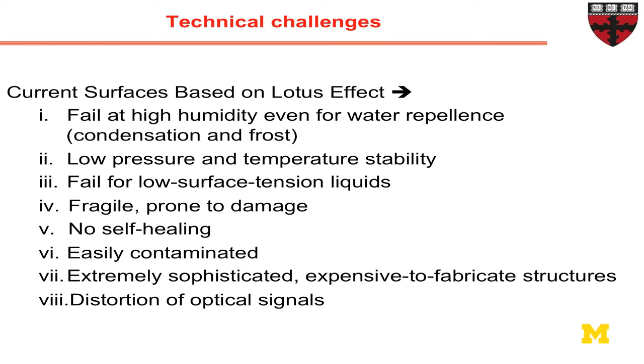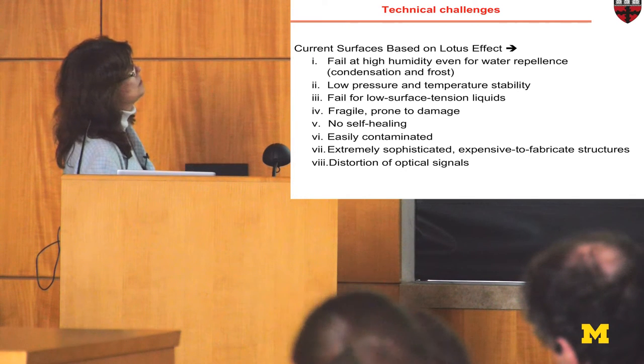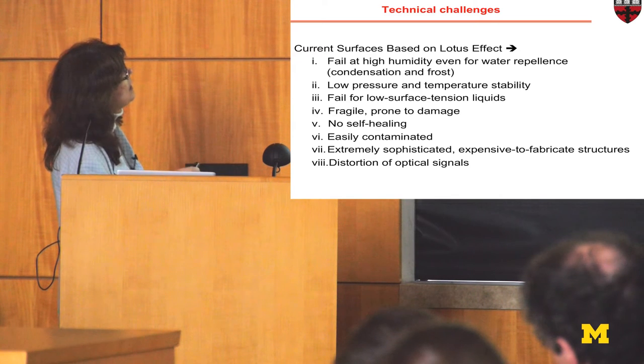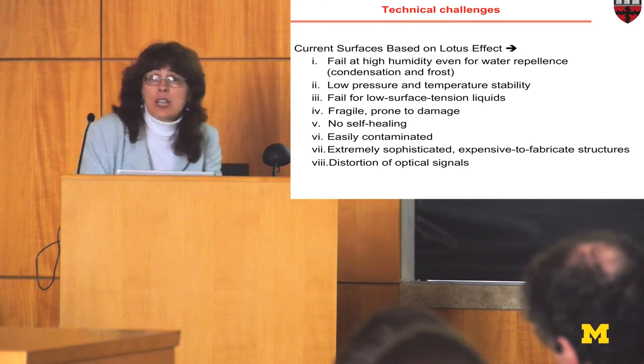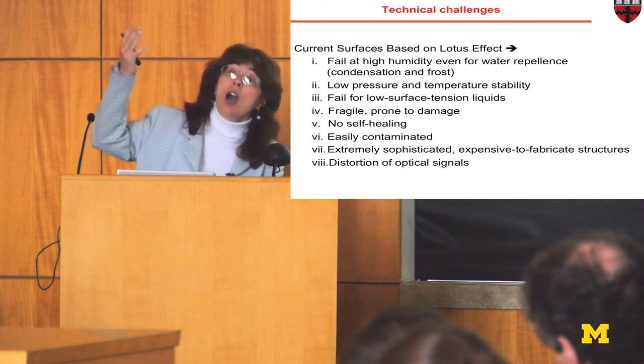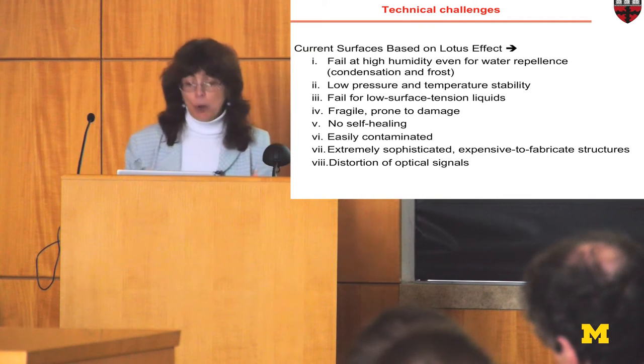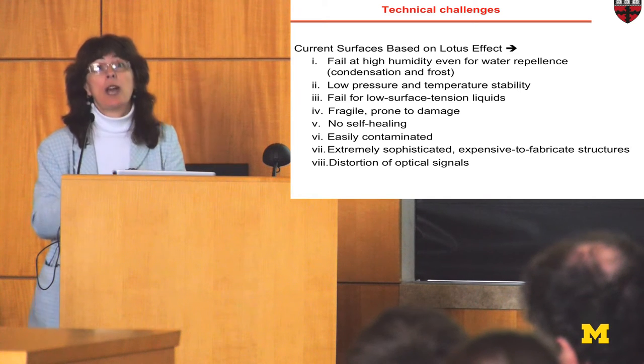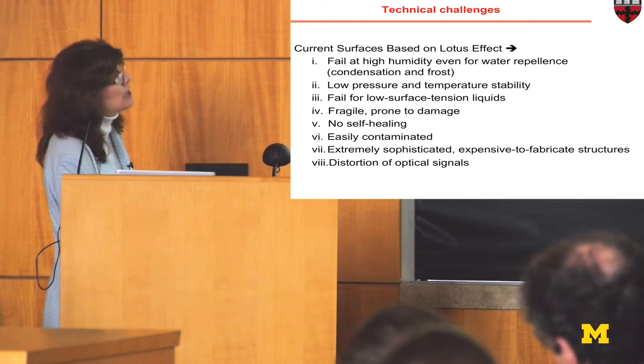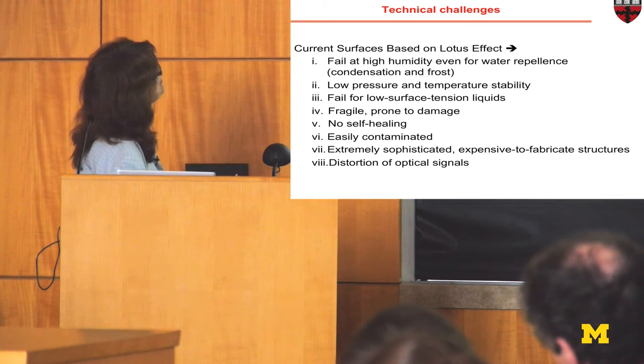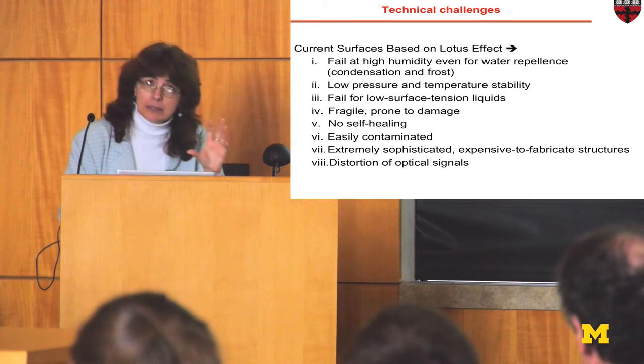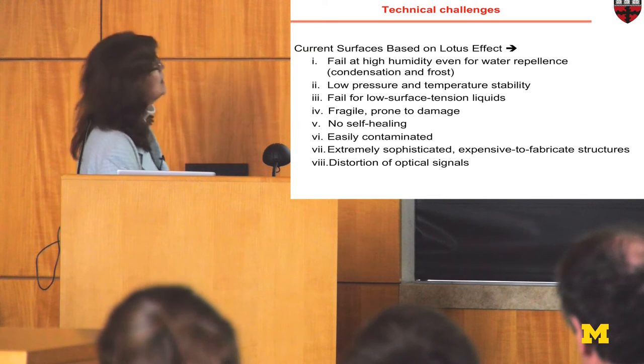And if we go further, really, unless we do something very special, the range of technical challenges with the superhydrophobic approach is pretty long. It can be solved one way or another, but in fact, we have to realize that they fail at high humidity and even for water repellence because of condensation and frost formation. They have very low pressure stability and temperature stability. For example, if you go to low temperatures, it's ice or frost. If you go to high temperatures, the properties of the liquid and energy change, so it becomes wet. So it certainly fails for low surface tension liquids, unless you do a lot of interesting tricks like the one I'm just doing here. Many of them are fragile. There are ways to improve their mechanical stability, but again, they're prone to damage.